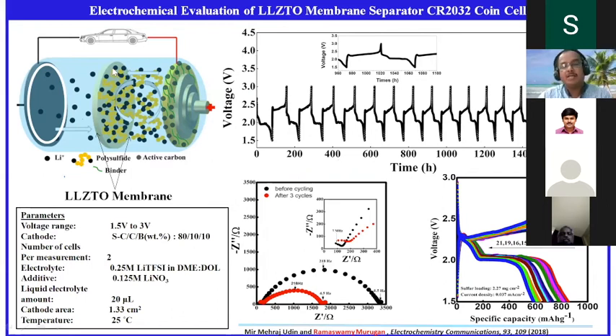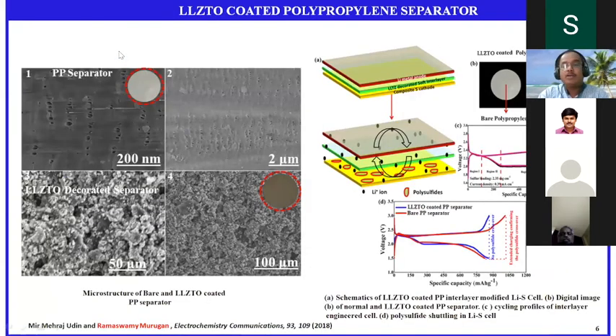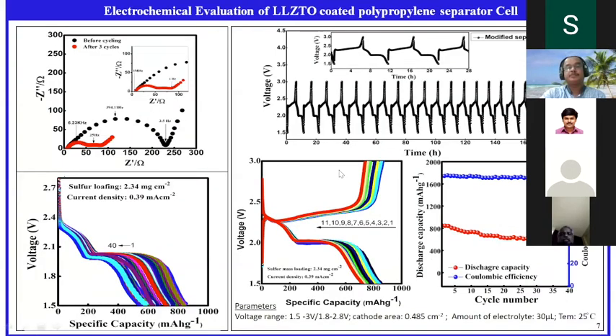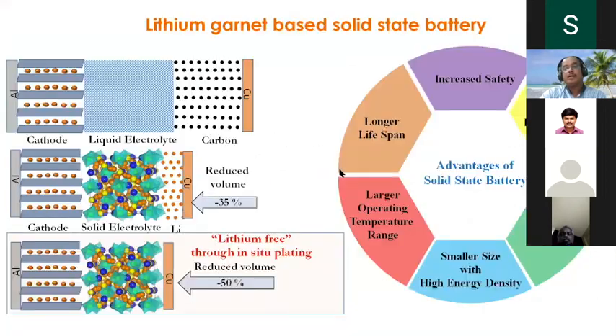But it was very thick. At that time we didn't have the membrane like what we have at present, 50 microns. Then we coated this LLZTO on polypropylene substrates. Then we could improve it. But still, we are working hard and looking for something else, to reach 50 micron garnet films, to improve the performance of the lithium battery. We are working. So what I can conclude.